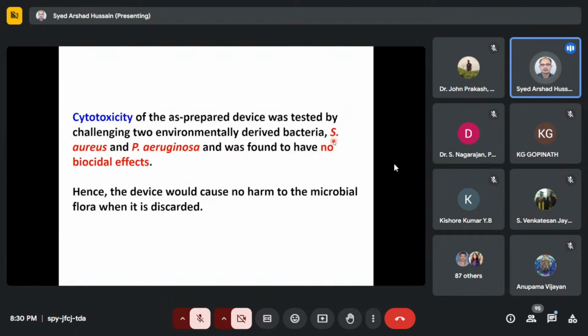Okay, and also we have exposed our device to environmentally derived bacteria, this S. aureus and another strain, and this is important because when you throw out your device in the environment, there are so many microorganisms. If it is eco-friendly, then the device should not harm the microorganisms in the environment. So we exposed our device to these two bacteria, and we found that hardly there is any effect on the bacterial growth, and it's unaffected. So we can say that our device is non-cytotoxic. So it's not affecting the microorganisms in the environment. So this is very good for the environment also. So it can resolve the e-waste issue also.